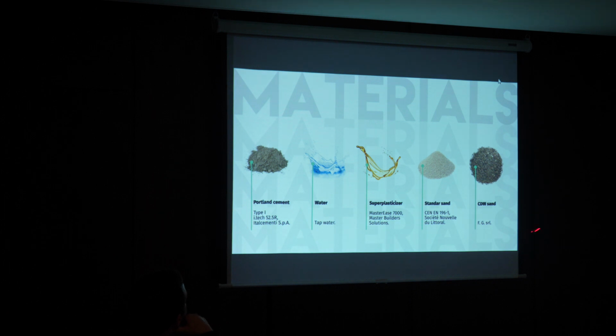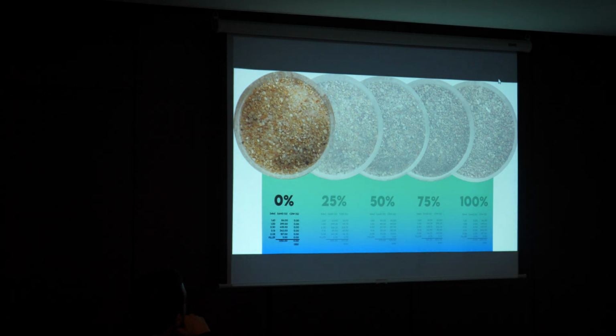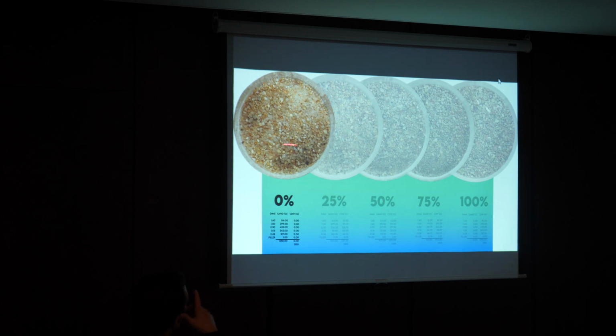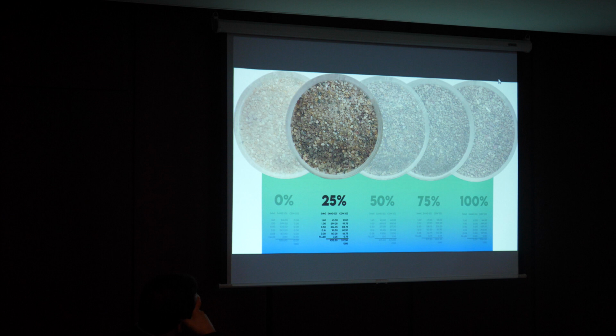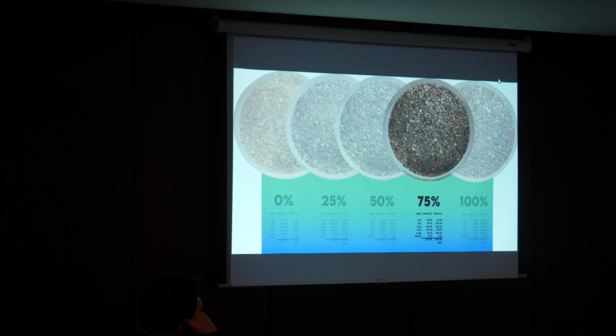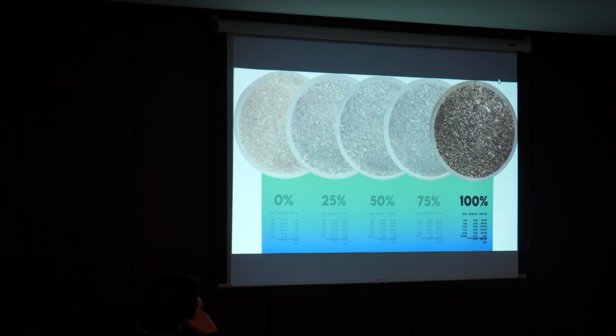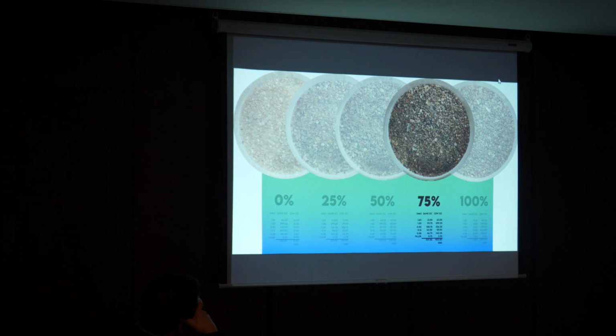For this research, specifically for the mortars, the materials used were the ordinary Portland cement, tap water, super plasticizer, and I'm going to explain why we implement this additive, the standard sand obviously, and the construction demolition waste sand. First, 5 batches of samples were prepared, starting with the reference one, in which just standard sand was used, moving to 25% substitution of the standard sand with the construction demolition sand, 50%, 75%, and 100%. It's important to notice that for the substitution, the sand was first sieved and each particle size was replaced one by one with the construction demolition waste sand.